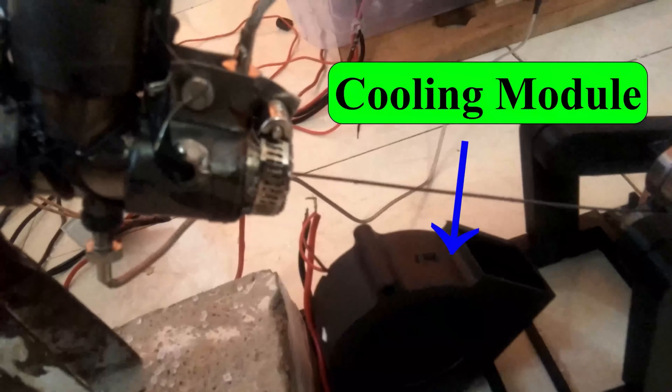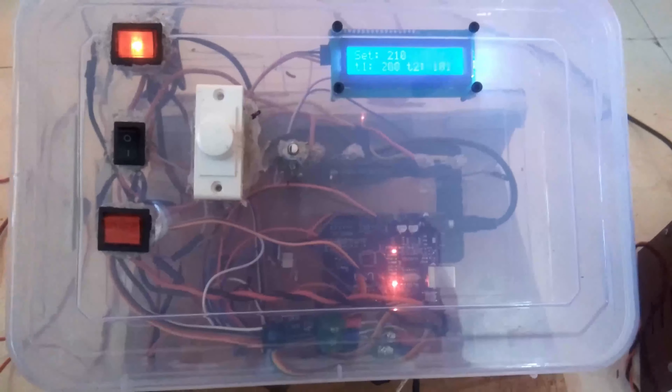while the cooling module quickly cools the filament. The alignment module ensures that the fibre is at the core of the filament, while the pulling module ensures a uniform pulling rate. The temperature control unit avoids solidification or fuming of nylon.